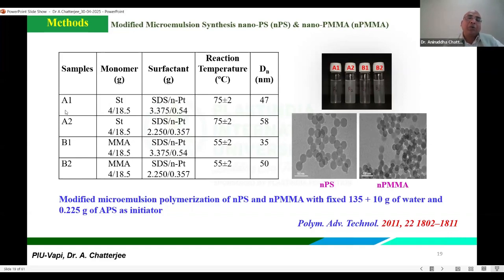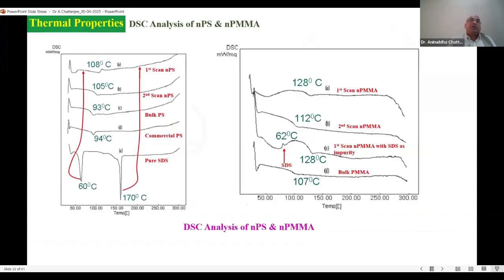And for A1 you get 47 nanometer size nanomaterials, whereas A2 is 58, and for methyl methacrylate that is 35 and 50. Here you can see A1, A2 and B1 and B2. So as the particle size decreases, transparency increases over here. You can see clearly that transparency increases with decreasing particle size. So this is about the differential scanning calorimeter analysis of polystyrene and polymethyl methacrylate.